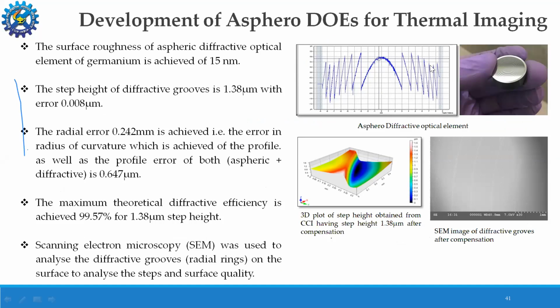This is a profile of the diffractive optical element fabricated, and the step height of the diffractive groove was achieved with the error of 8 nanometers. Since we are talking about nano machining, error is also in nanometers. And the maximum diffractive efficiency we could achieve was 99.57%. Further, scanning electron microscopy was used to analyze the radial rings on the surface to further analyze the steps and surface quality.